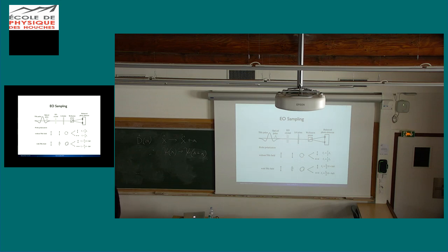It's a trade-off between how efficiently you can generate the 1.5 microns and whether you can live with a slightly lower chi2. The reason why we use the organic crystals is that for a lot of our samples, we're trying to push to the higher end of the frequency range. A lot of the phonon resonances that we're interested in driving are around 3 terahertz. The other advantage of the organic crystals is they have a higher cutoff, and we can generate higher fields.